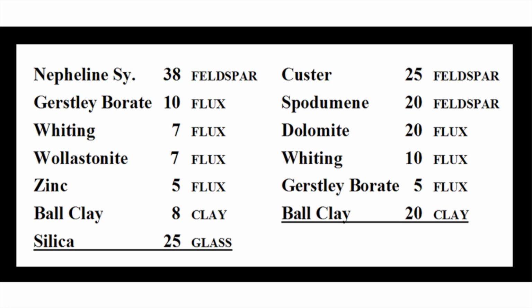And lastly, again, the feldspar content in both glazes is the highest and the bulk of the glaze. One of the glazes has a high amount of Gerstly borate, a strong, low-melting flux. And thirdly, one of the glazes is very high in silica. The other glaze has no extra silica. So the glaze on the left is a glossy glaze, and the glaze on the right is a matte glaze.